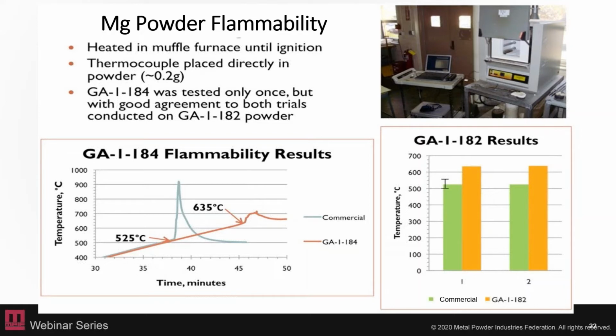So even though you're working with a specific material that you may think is traditionally explosive or non-explosive, how that powder has been produced and how that surface has been changed, modified, or controlled really can affect your flammability. So in this case, the powder is extremely stable and would be more stable than many of the traditional powders that we would deal with.